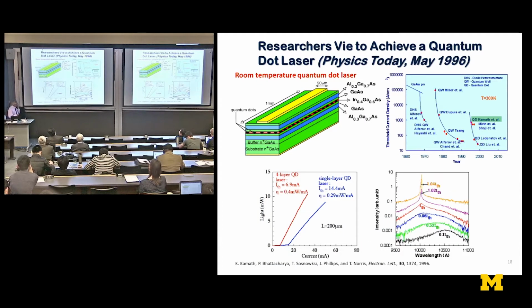So now that we knew what we were doing, we ventured to actually grow a laser heterostructure. And we made the first laser that actually worked at room temperature. And we sent it for publication the moment we got the results. And Ted Norris did some of the time resolved measurements, which are not shown here. We sent it off, and we sent it to Electronics Letters. Now, Electronics Letters has an impact factor of, currently it's less than 1.